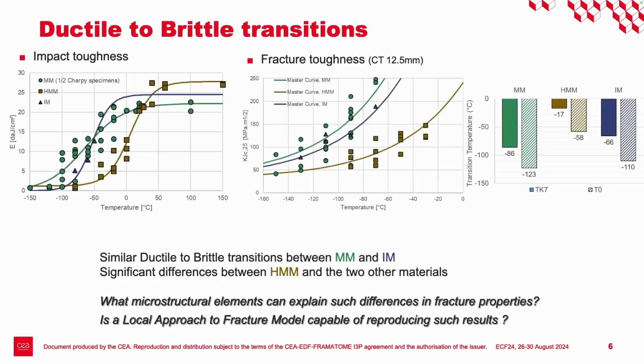Then, as regards the ductile to brittle transition, Charpy impact toughness tests have been performed, as well as fracture toughness tests, also at EDF. And as you can see now, the first model material and the industrial material have almost the same behavior, the red points here and the blue points for Charpy impact toughness or fracture toughness tests, while the homogeneous model material has a much larger transition temperature, but again, they have the same chemical composition.